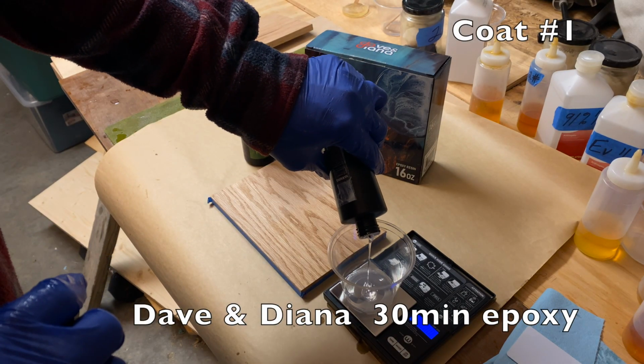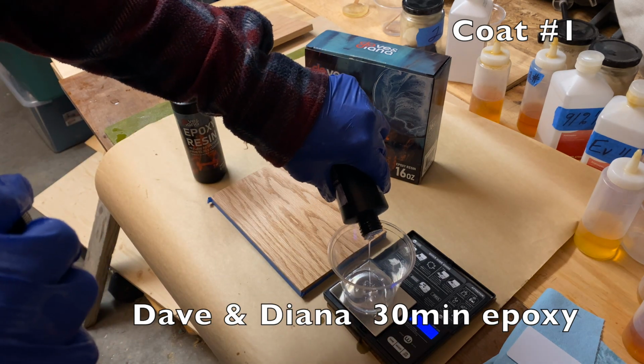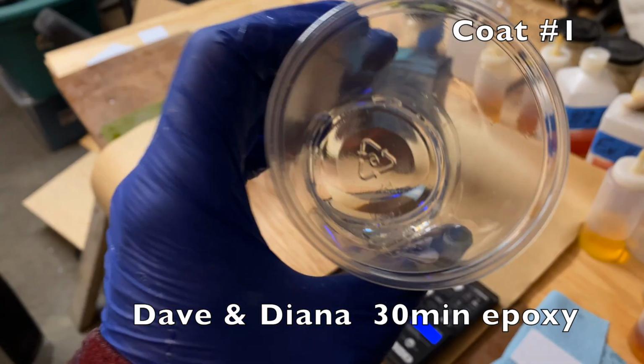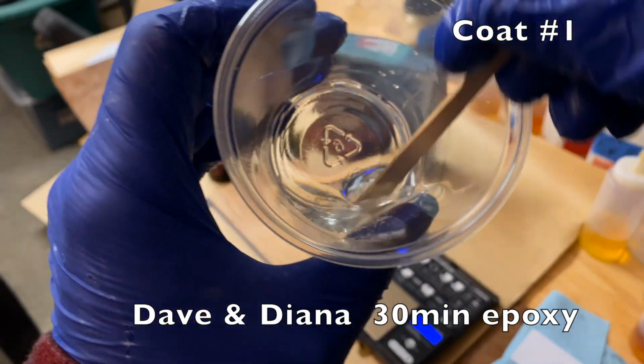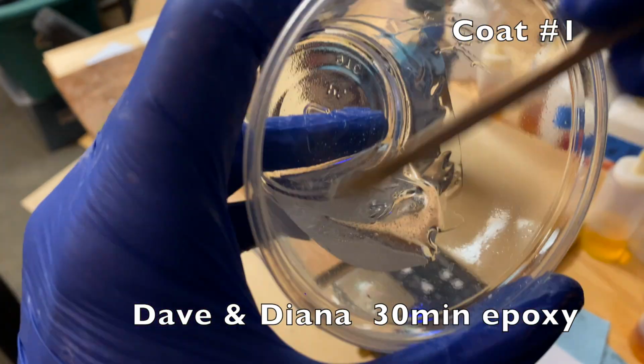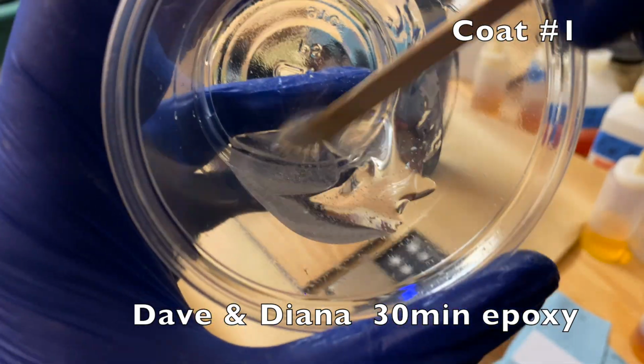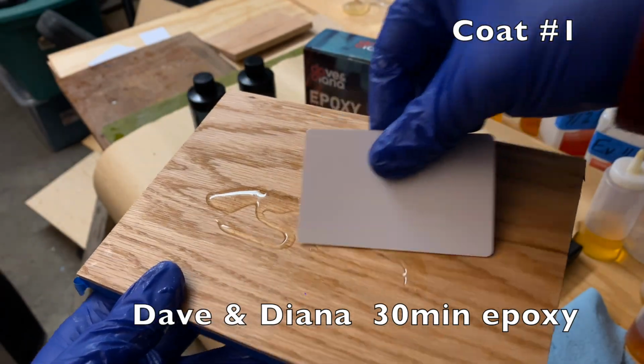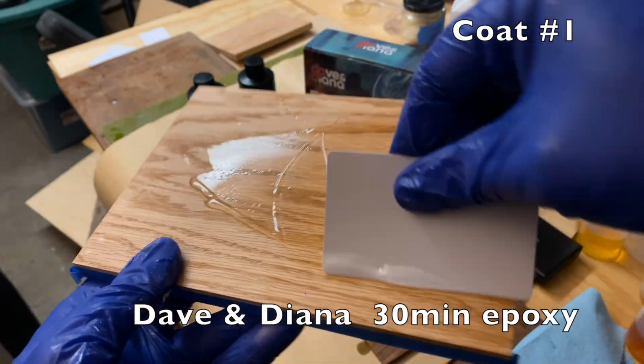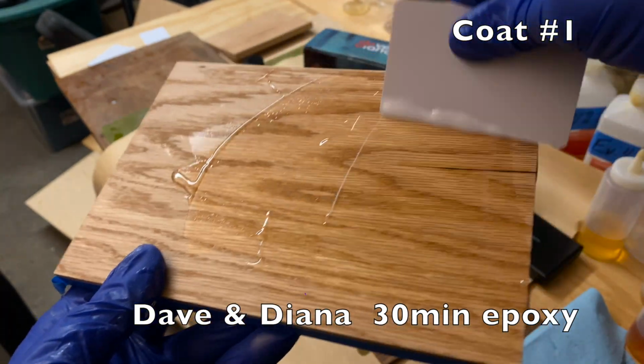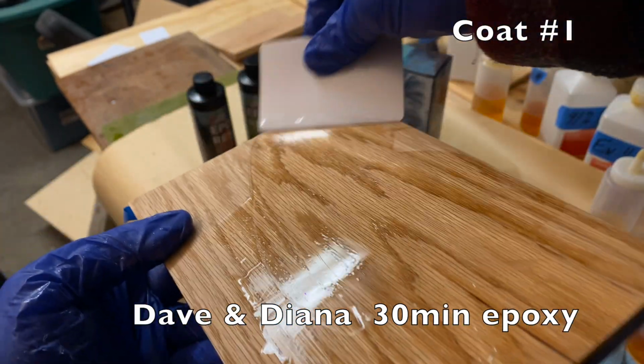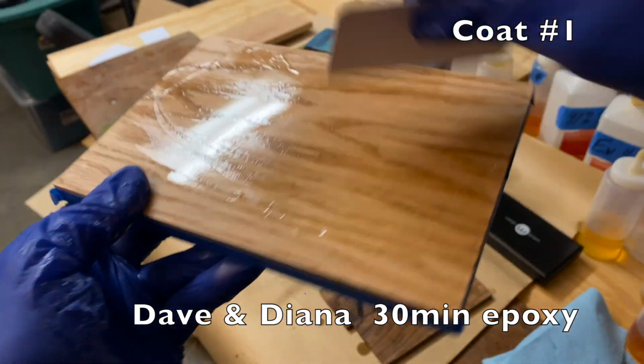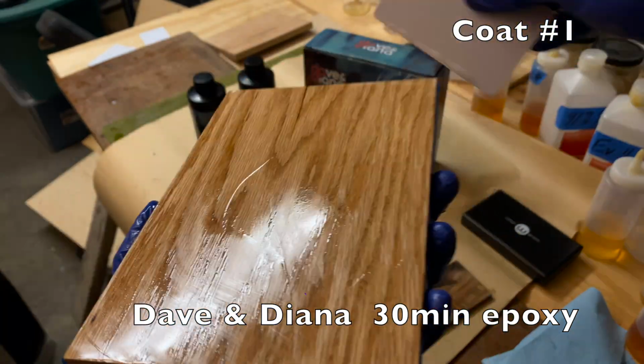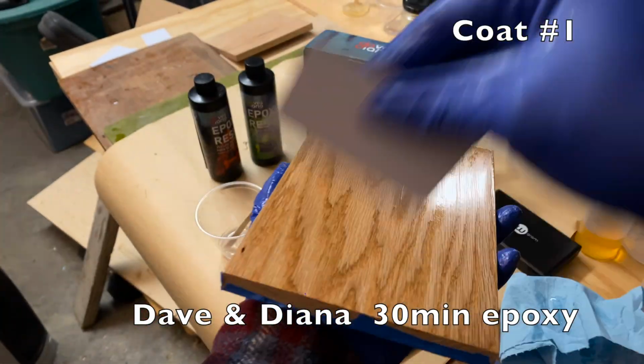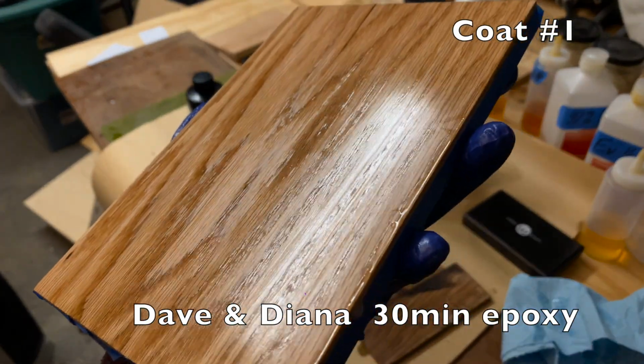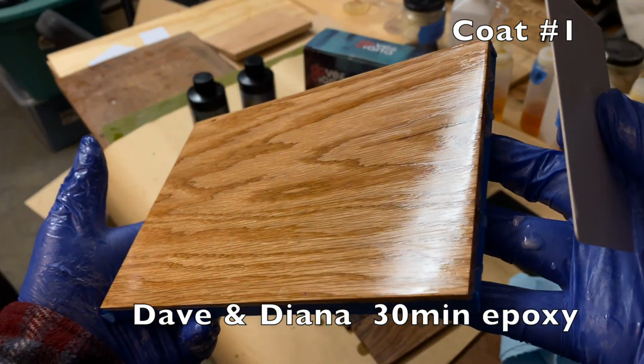Next, we'll try the Dave and Diana epoxy resin. This was the cheapest of the bunch at $10 for 16 ounces of epoxy. That's 8 ounces of the resin and 8 ounces of the hardener. In contrast, the Z-poxy finishing resin was almost $29 for 12 ounces. The epoxy mix is clear, unlike the previous Z-poxy finishing resin, which had a slight amber cast during the mixing. They both spread very smoothly and are easy to work with, especially given that they have a 30-minute working time if needed. Now this one's ready to dry for 24 hours before sanding.